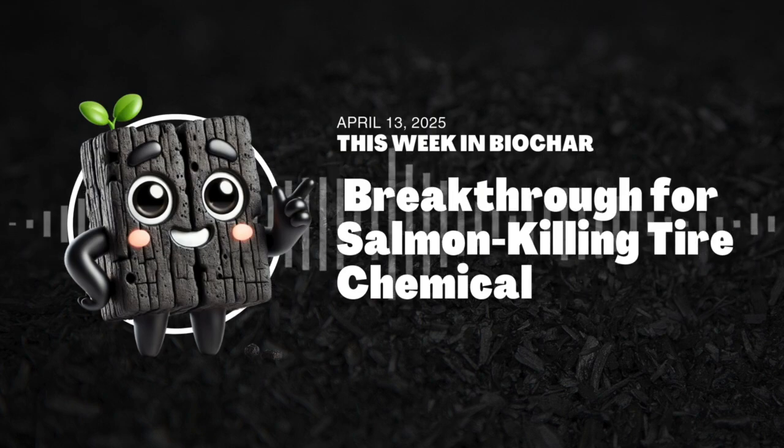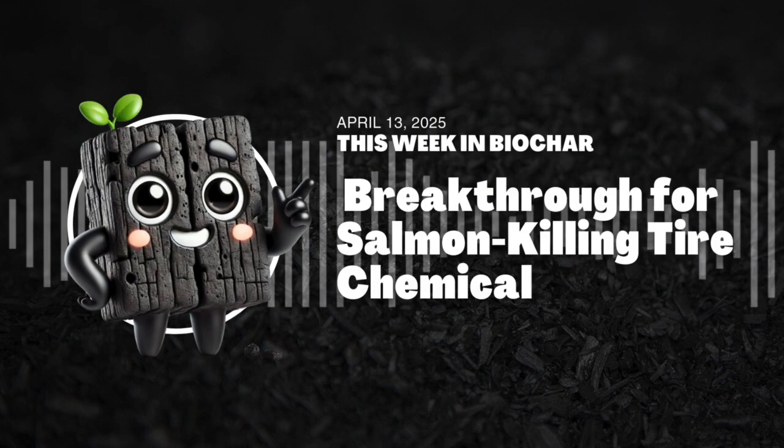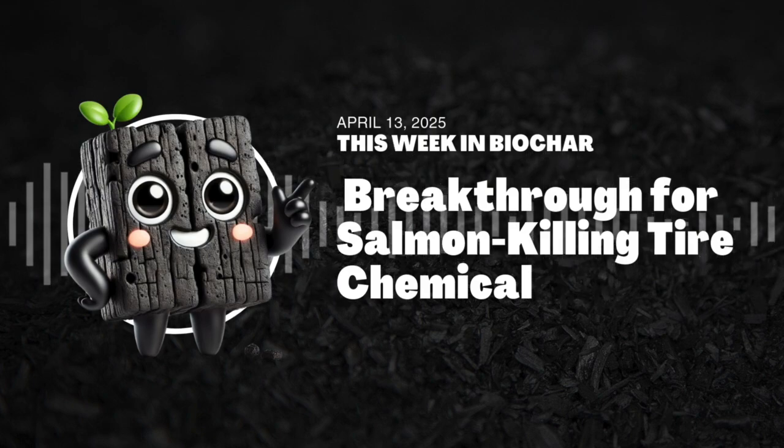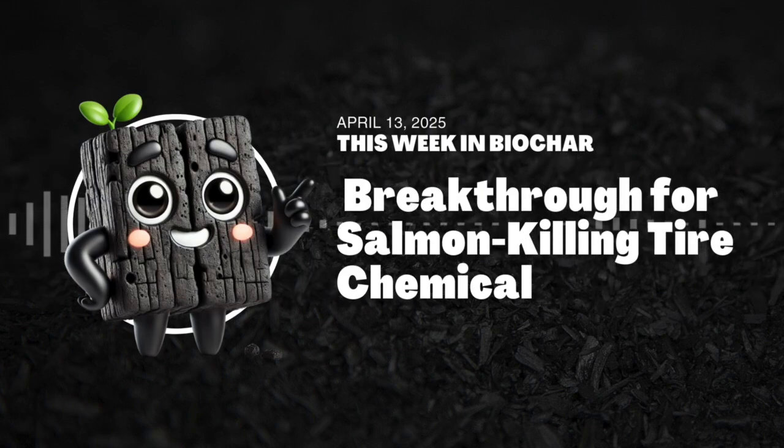Well, the numbers are pretty impressive. They measured an increase on average of 250 square meters per gram. Whoa. Yeah. And the pine bark biochar they started with already had about 200 square meters per gram, which is decent. So this process can more than double it. In some cases, yeah. A really significant jump. That's probably why it caught people's attention over at Biochar Today.